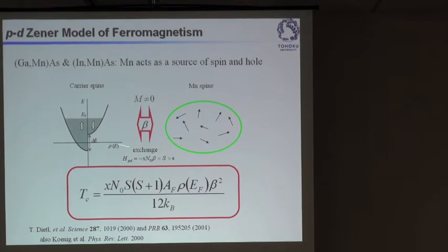So if there is an exchange interaction, and you introduce a finite magnetization in this system, you increase your free energy because you have introduced order in the system. But because of this exchange interaction, you get the spin splitting, and you always reduce the carrier energy here. And this free energy increase can be reduced by reducing temperature. And that means that at some temperature, this energy increase and energy gain balance, which is the transition temperature given here. So our transition temperature can be calculated if you know this exchange constant, and also the band structure, and if you assume the carrier concentration, we know where EF, the Fermi energy, is, and we can calculate the transition temperature.